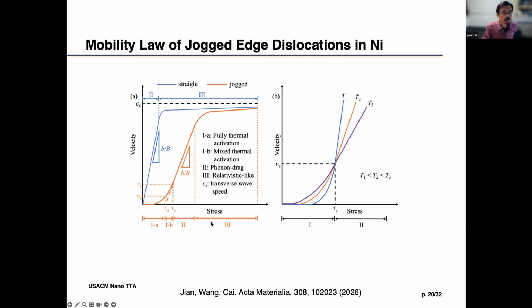Now, since then, we did a more systematic study trying to come up with a mobility law that can be used to consider the jogs in discrete dislocation dynamics simulation. This is a schematic of what is happening. If you don't have jogs in FCC, you move in two regimes. First you have a linear mobility law, but when you go really, really fast, it has to be limited by the sound velocity. So it goes from linear to the relativistic regime. But if you have jogs, then you have an initial non-linear regime, because of the jog, the motion becomes thermally activated. And if you overcome the thermal activation by stress, then you go to the linear regime and then again the relativistic regime.